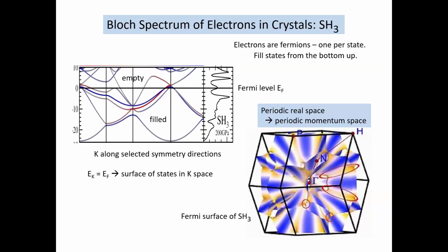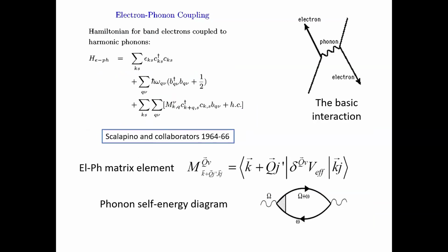But it's not just looking at this. You don't learn that much about why it's superconducting. What you have to do in the theory, and I'm not going to go through this, and the computational theory, is to describe this main interaction: an electron with momentum k and one with momentum k prime coming toward each other. This one emits this quantized phonon over here and scatters to k prime. This one absorbs it, scatters to k prime. That's the primary interaction in a superconductor. That's important here. The momentum transfer, k prime minus k, is q.